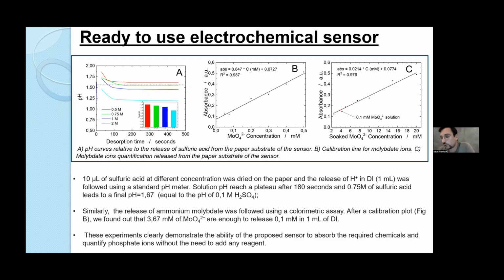A similar approach was made to understand how much molybdate ions we had to let absorb on the paper, and we found out that 3.67 millimolar of molybdate ions are enough to release 0.1 millimolar in 1 ml of water. So this experiment clearly demonstrated the ability of the proposed sensors to absorb the required chemicals and to quantify phosphate ions without the need to add any reagents to the solution.